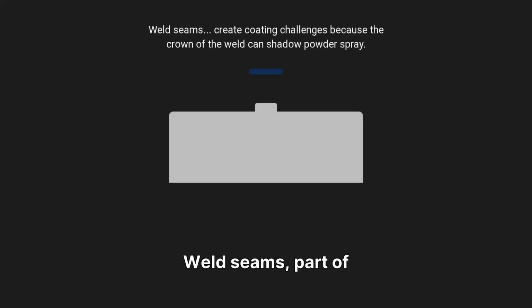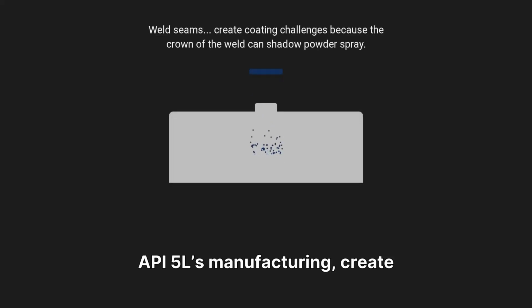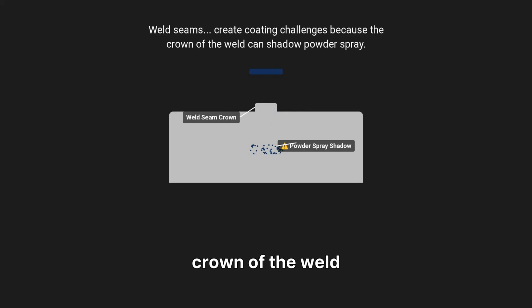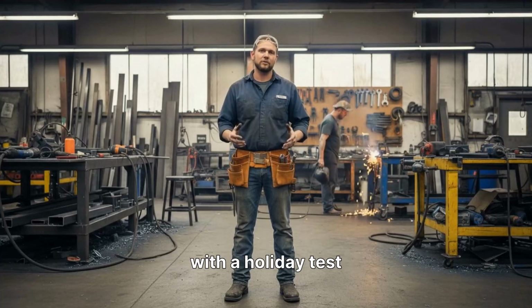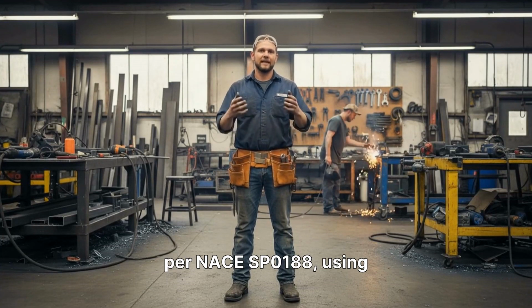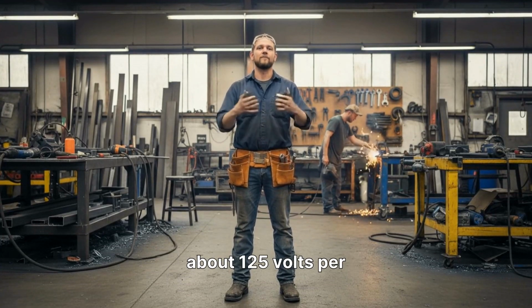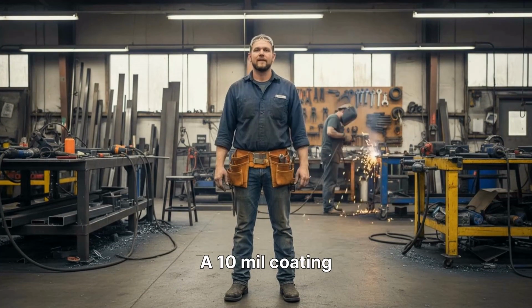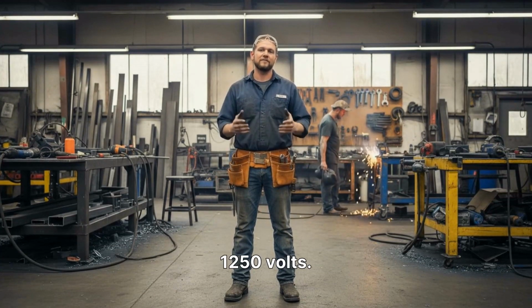Weld seams, part of API 5L's manufacturing, create coating challenges because the crown of the weld can shadow powder spray. Once coated, verify continuity with a holiday test per NACE SP0188, using about 125 volts per mil of coating thickness. A 10 mil coating should be tested around 1,250 volts.